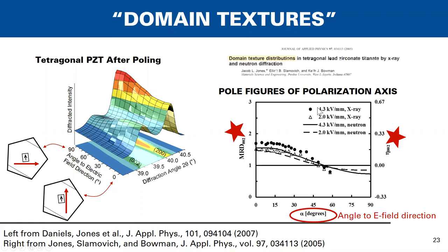Okay. Now, if you fit all of these diffraction peaks and you calculate the degree of domain switching, you can represent that as a pole figure. Okay. So here I have a pole figure for this material, tetragonal PZT, MRD on the left y-axis, eta on the right y-axis. Again, you can calculate one from the other. And we're representing data here as a function of angle to the electric field direction. So this is the first pole figure that we see today because it describes the crystallographic texture or preferred orientation of the 002 pole as a function of angle to the electric field.